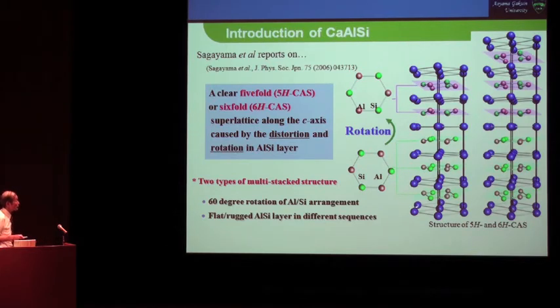So we call it 1H CAS when every silicon-aluminum layer has the same starting point. However, 5H CAS has a 60-degree rotation after 5 layers, and 6H CAS has a 6-layer rotation.